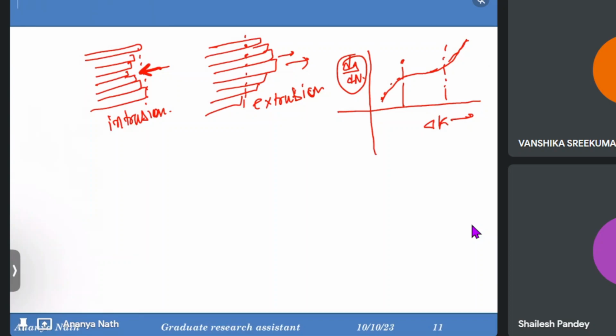So this crack growth may take place due to the intrusion or extrusion. But it's not always true that only the sharpening of the tip will take place. A blunting of the tip may also take place, because it's not a plain matrix or alloy, it's a composite. There the interface is also taking part in the fracture, and there are some particles as well. Where the crack is growing, if in the middle some particle is seated over there, then the crack may not grow, or it will grow, or it will just overcome the barrier of the particle. It may not overcome, it will get a blunt tip at the end, every possible thing can happen.